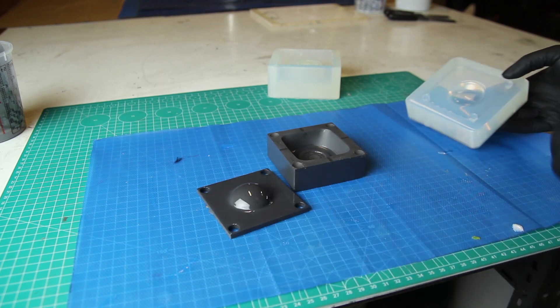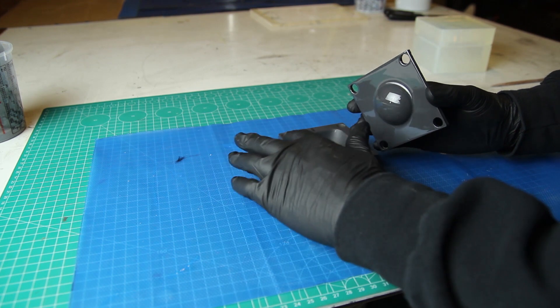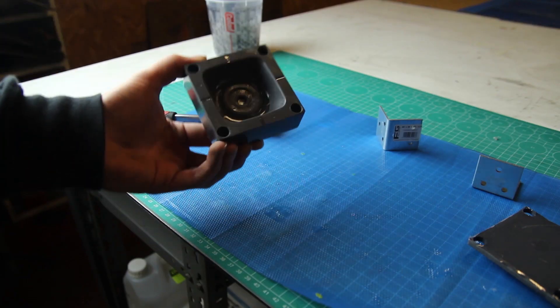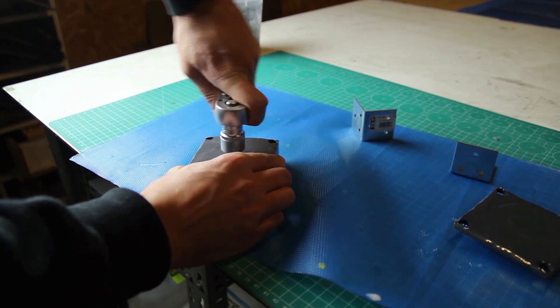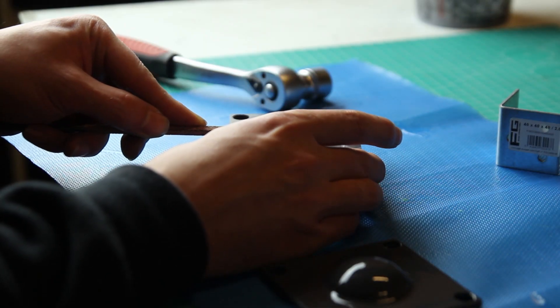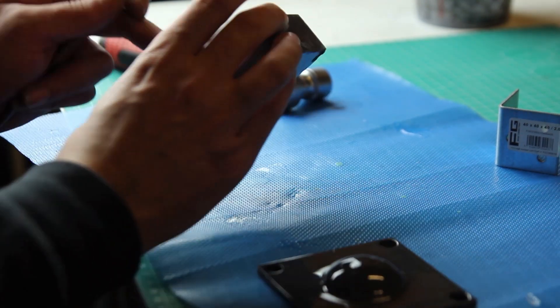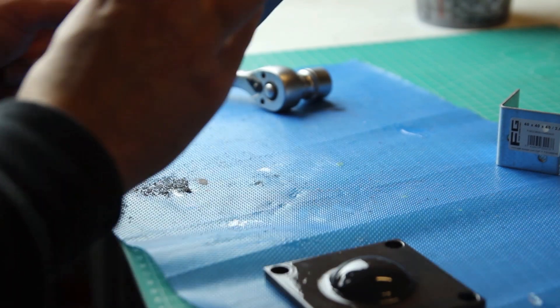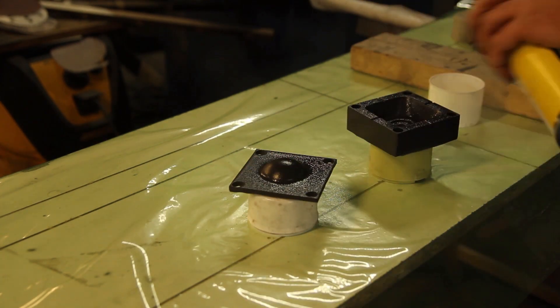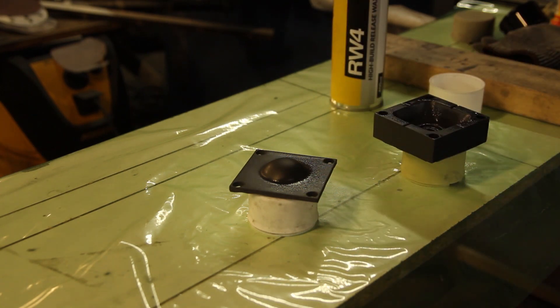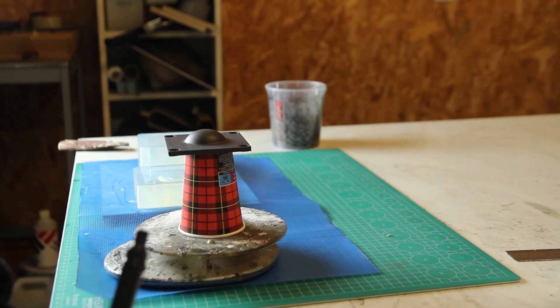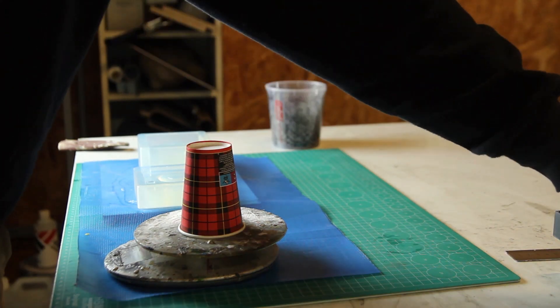Here's the first sample, trying to test fit the molds. Everything looks good. This is a durable plastic, it's a 2K so it's hardened and won't soften under high temperatures like till 60-70 degrees. The advantage is to go quite rapidly through the prototyping. Epoxy would cure in about 12 to 24 hours or even more and requires post curing. The polyurethane is a fast way to go through this process. Another advantage is that now I know how much resin is needed, so what the volume is of the product.